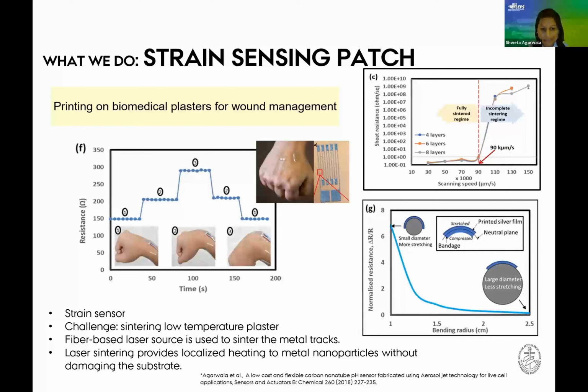And what we basically have shown as a proof of concept here is that it is totally possible to print and functionalize the inks onto these plasters, and then you can get an actuation motion out of it, and you can detect the motion of the wrist, for example, in this case.